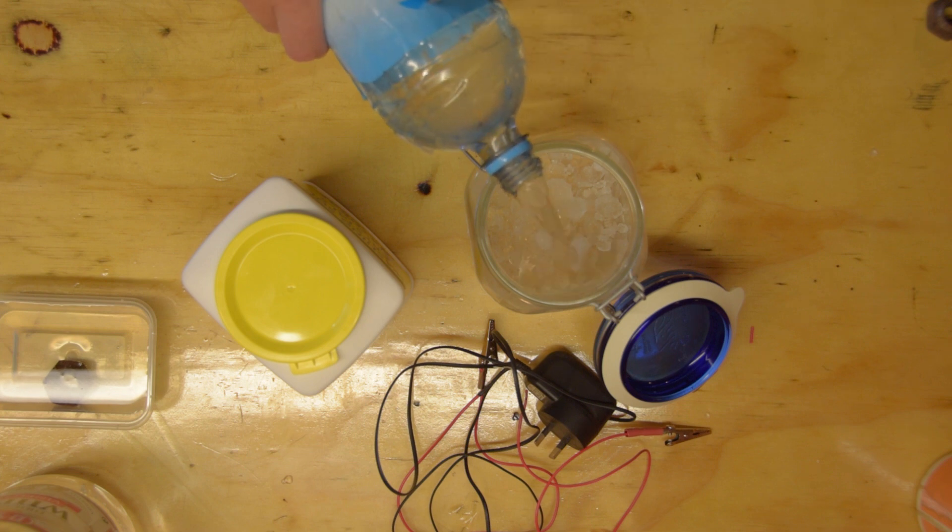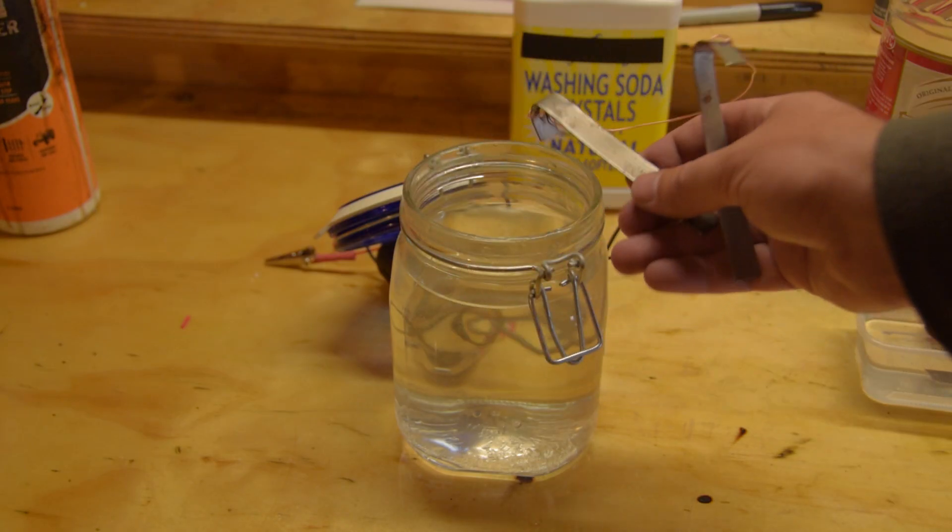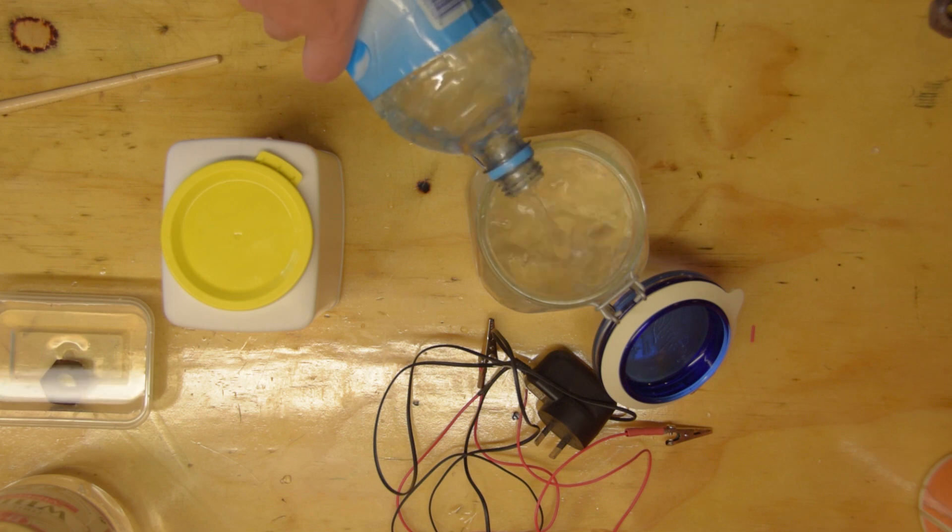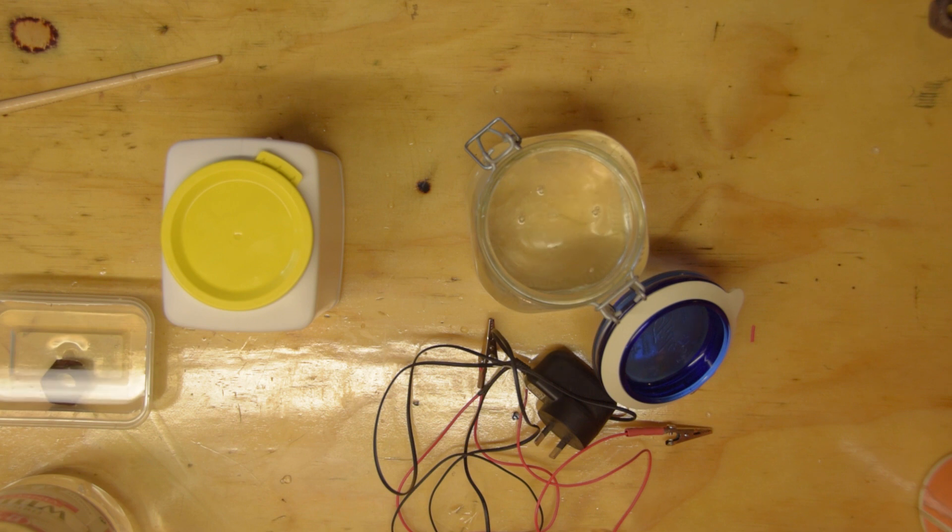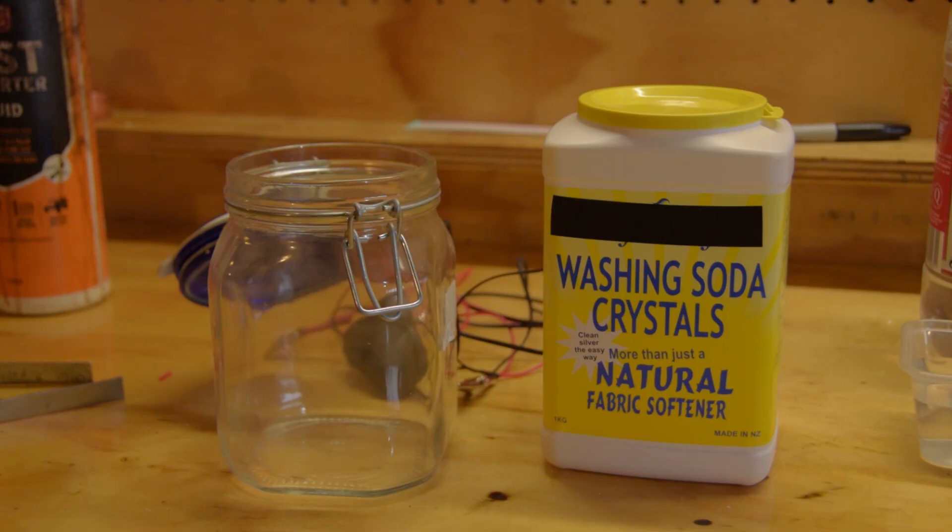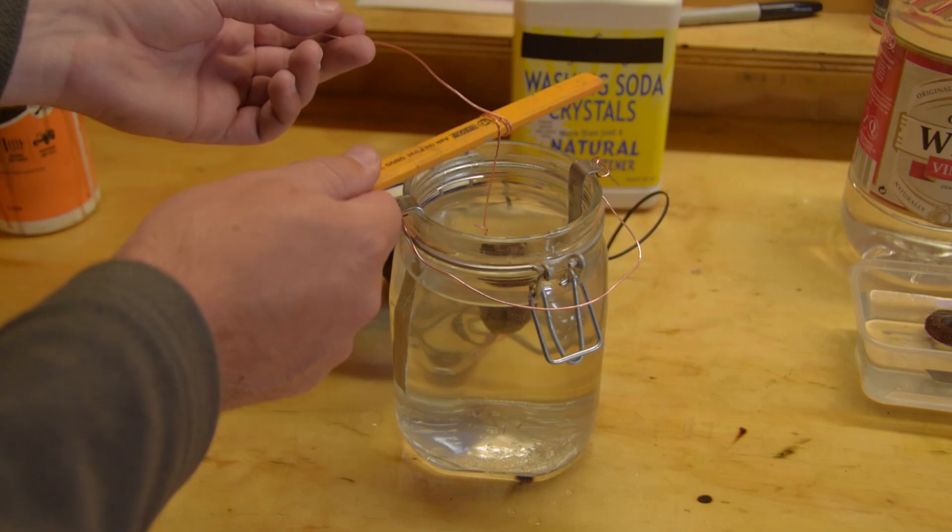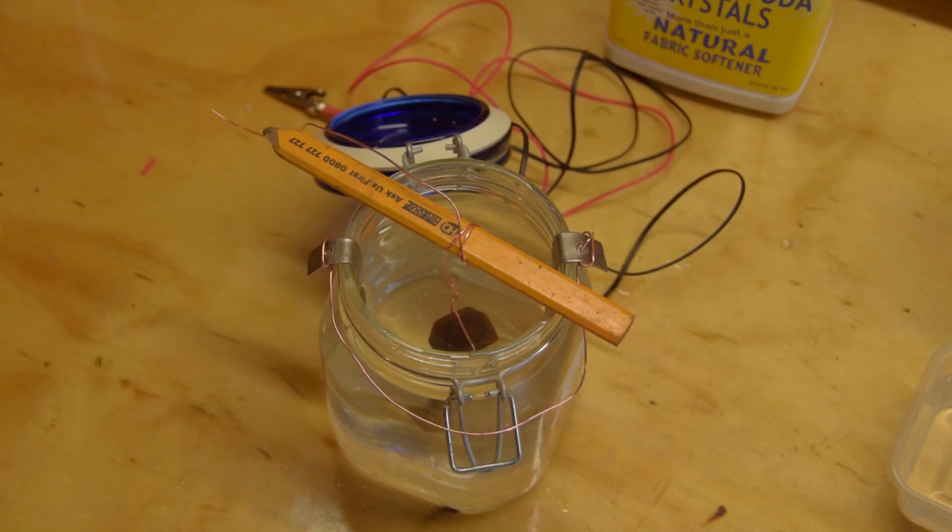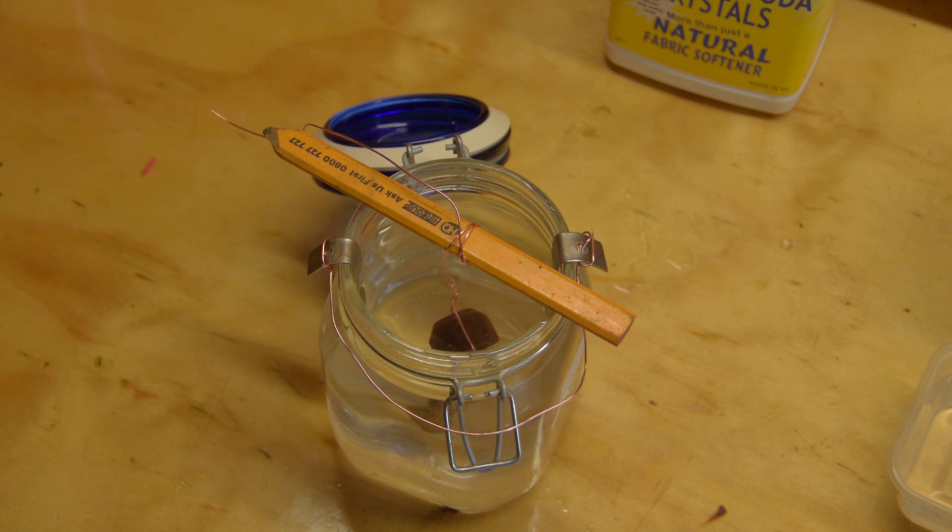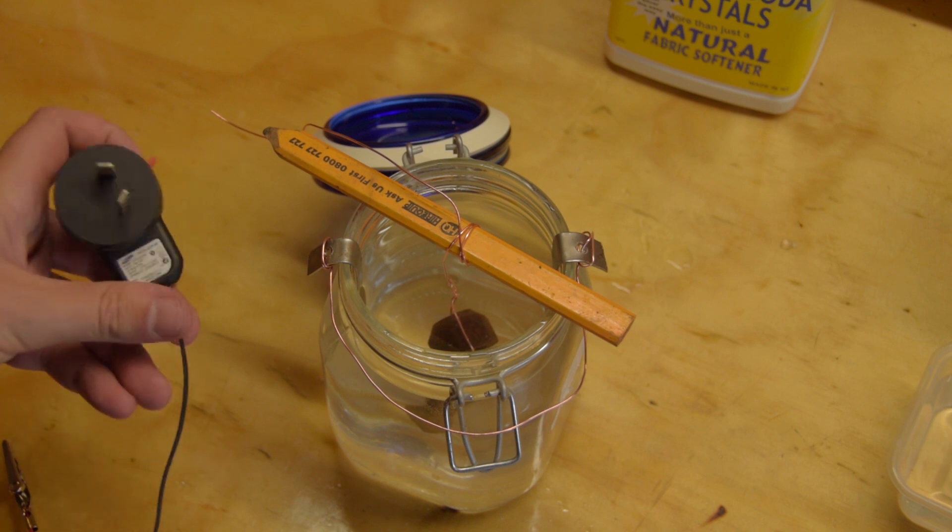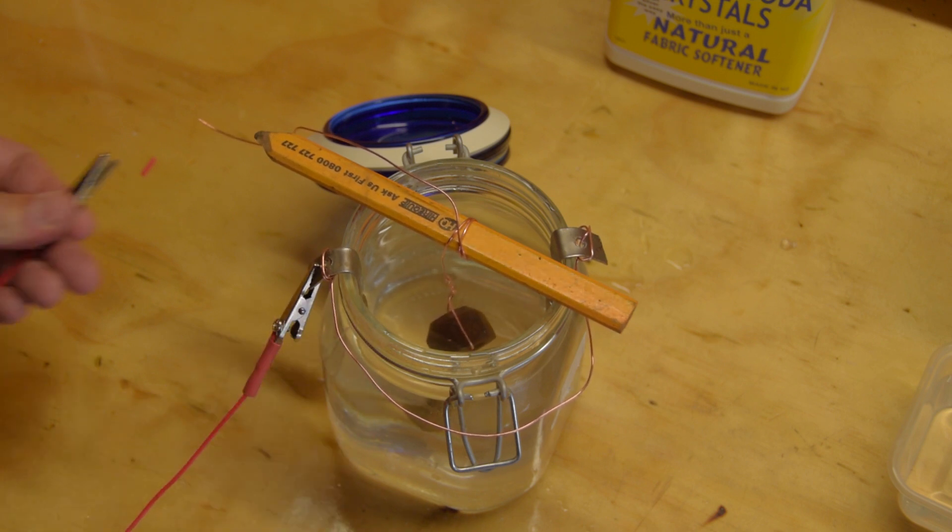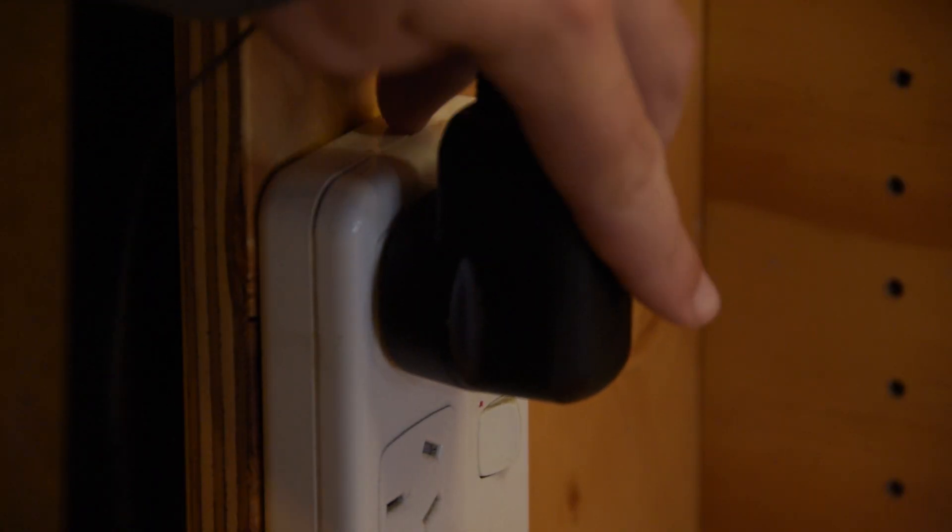What you'll need is a container of some sort. Plastic or glass. An old cell phone charger or any other low current power supply. A strip of steel. This will be the anode. An extra piece or two will allow you to spread the current out around the container, but it's not necessary. The jar will be filled with water, just tap water. Before I filled the jar with water, you saw me add washing soda, sodium carbonate. This is what you'll see everyone use for electrolysis. But I want to point out that sodium carbonate plays no part in the rust removal process. Its only role is to increase the conductivity of the water. I think this will work fine with just water, though it'll take longer with the equivalent amperage. Alternatively, you could also increase the conductivity with a spoonful of table salt. But that will give off chlorine gas. Unless you're huffing the jar, I doubt that'll be an issue. But I suggest just use washing soda like everyone else. It only costs a couple of dollars.